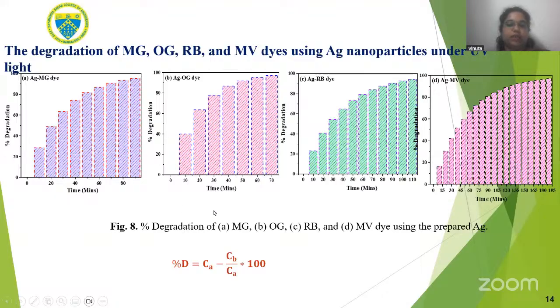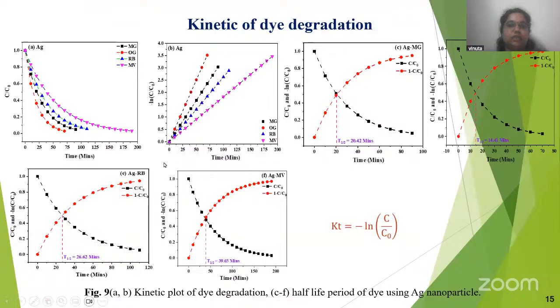So percentage of dye degradation was calculated by using this formula, that is (Ca − Cb) divided by Ca into 100. So from that we can calculate the percentage of degradation. So next is the kinetics of the dye degradation. Kinetic study plot illustrates the progressive degradation over the time, confirming that the degradation process follows first order kinetics. As the time interval goes on, a decreasing trend is observed.